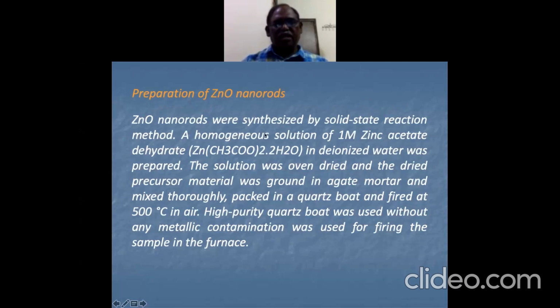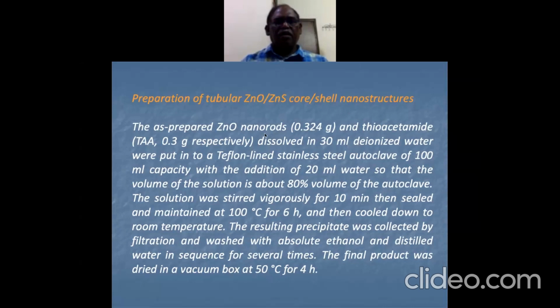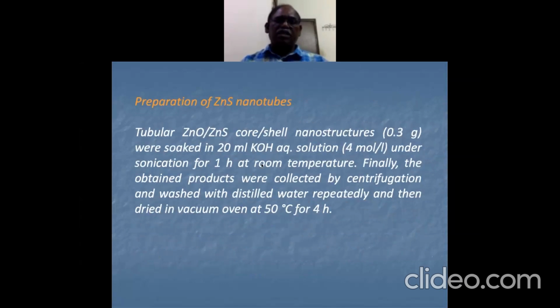And here, then, you can also really form the ZnO core shell structure. And if you just soak this kind of structure into KOH aqueous solution, this ZnO gets dissolved, and you can also form very beautiful ZnS nanotubes. So for many applications, because the surface area now increases from the outer side and inner side also, for some kind of gas sensor applications and other sensor applications where you need more surface area, these nanotubes could be used.